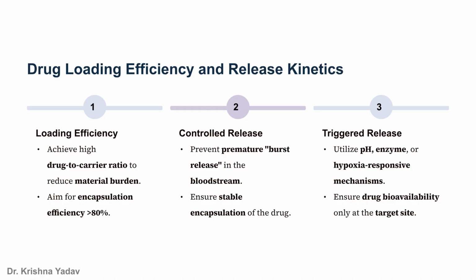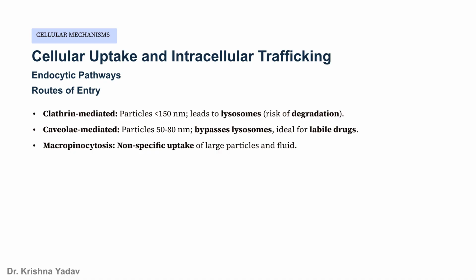Effective drug loading requires a high drug-to-carrier ratio and high encapsulation efficiency. Controlled release prevents premature burst release. Triggered release, using pH, enzyme, or hypoxia mechanisms, ensures drug bioavailability only at the target site. Cellular uptake occurs primarily through endocytic pathways. Clathrin-mediated endocytosis often leads to lysosomal degradation, while caveolae-mediated pathways bypass lysosomes. Macropinocytosis is a non-specific route for larger particles.